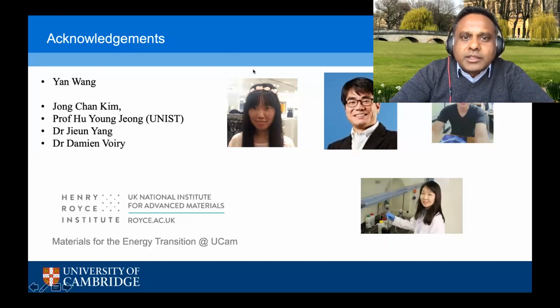Why is there no damage at all caused by kinetic energy transfer for indium contact on MoS2 during e-beam evaporation? We know the damage happens in Au contacts on MoS2. Is it because the melting point is much lower? Yes, exactly. That's exactly right. Indium is very soft, so the amount of power that we need to apply to the crucible is very low, which allows for very gentle deposition without damage.